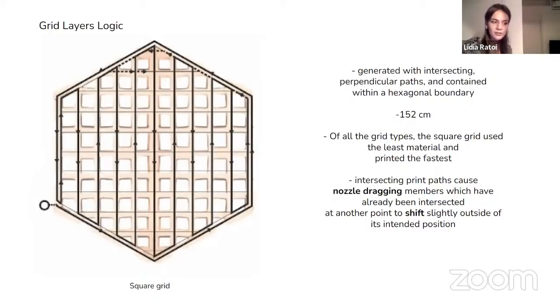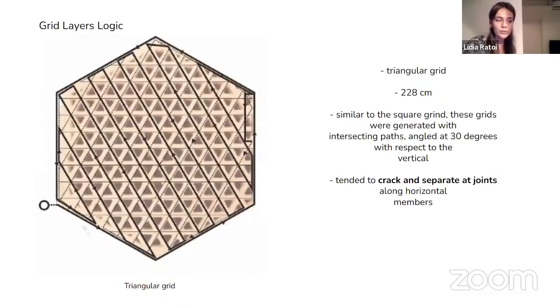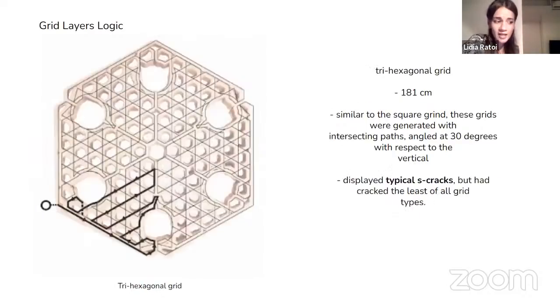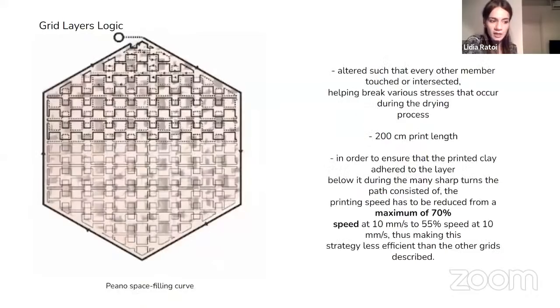Then we tried with a triangular grid, but the printing lines were too long. It was cracking when it was drying. Then we tried a trihexagonal grid, but it was also cracking when it was drying. So then we experimented with a space filling curve, but the tiles became too dense and there was too much material use. Printing time was too long.